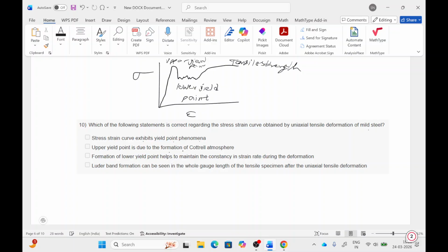Upper yield point is due to the formation of a Cottrell atmosphere, which is the solute atom interacting with dislocation. This condition from a Cottrell atmosphere shows some strength during tensile testing. So first and second are correct. Third option: formation of lower yield point helps maintain constancy in strain rate during deformation—this is also correct, as it's required to maintain the strain rate. So first, second, and third are correct.